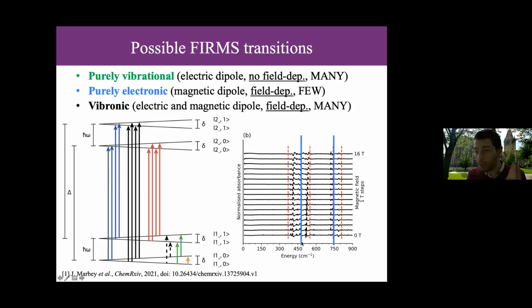So anything below that must be these intra Kramer's doublet ones, because we're not able to do these inter Kramer's doublet vibronic transitions, because that would have to be over the electronic energy. It would be the first electronic excitation plus a vibration. So that's on the right-hand side of this blue line. So anything on the left must be these intra Kramer's doublet vibronic transitions. It can, of course, also be a hot transition, but these spectrum are at 4 Kelvin and they trail off incredibly quickly due to population of this excited vibrational state. So it's mainly dominated by these intra transitions.